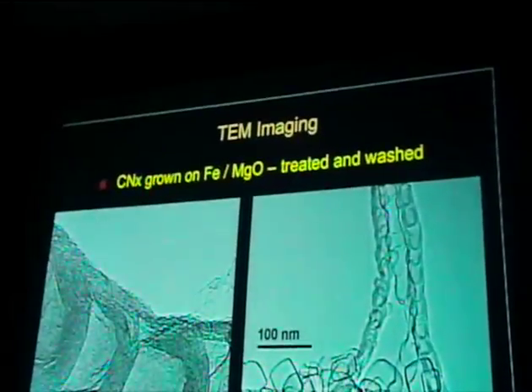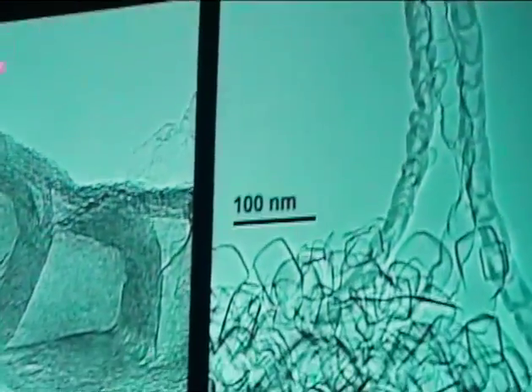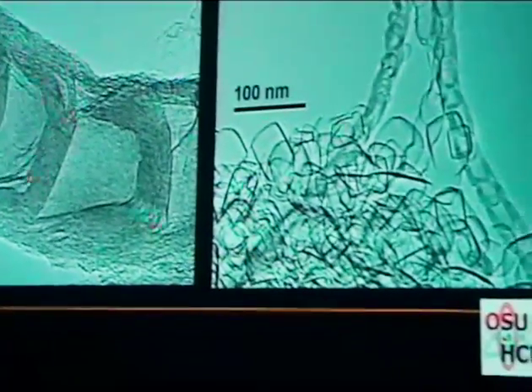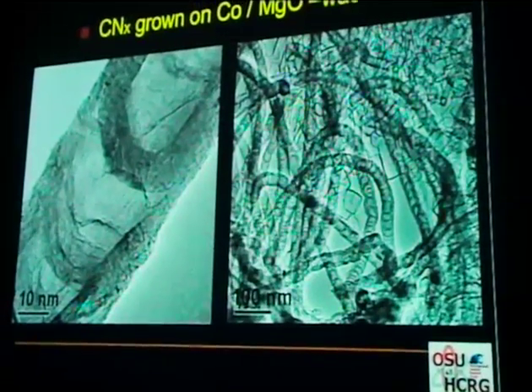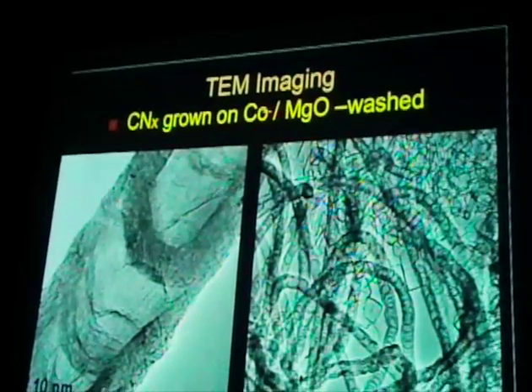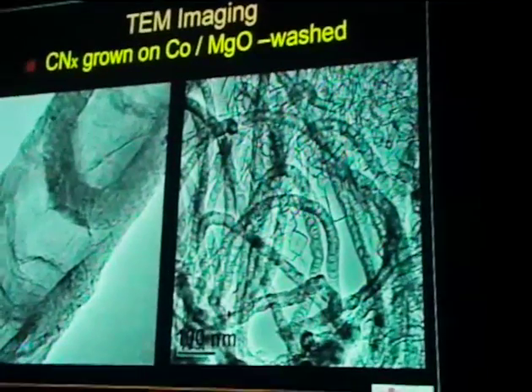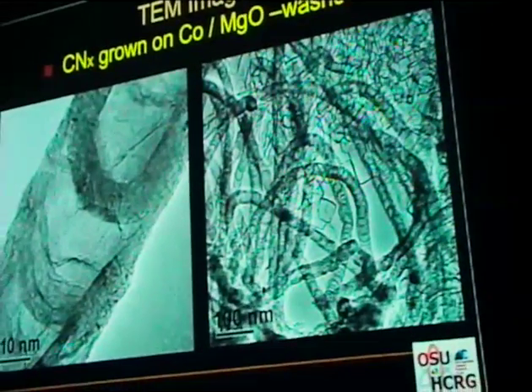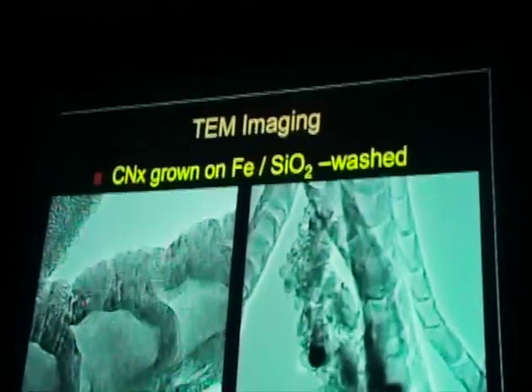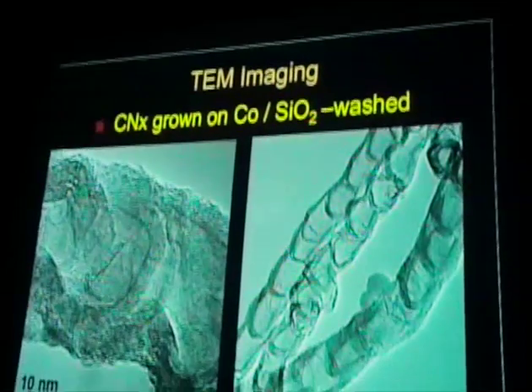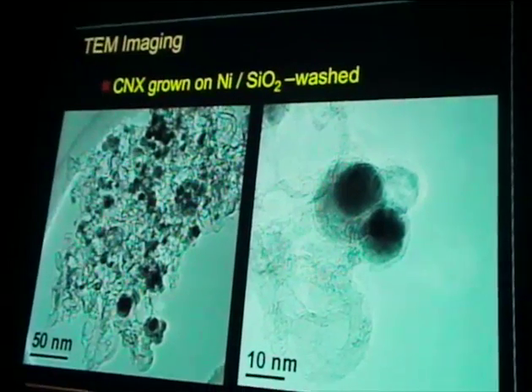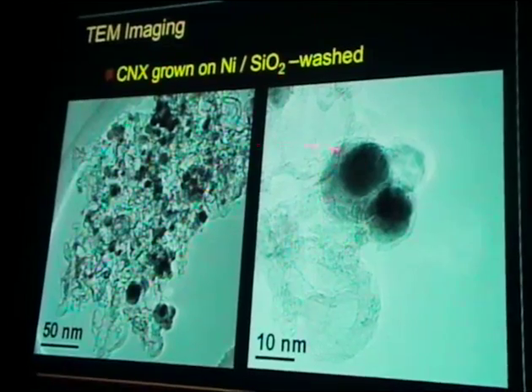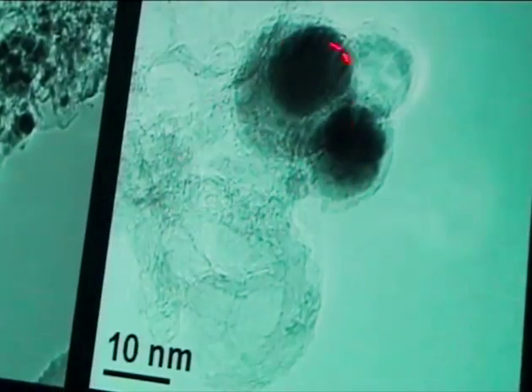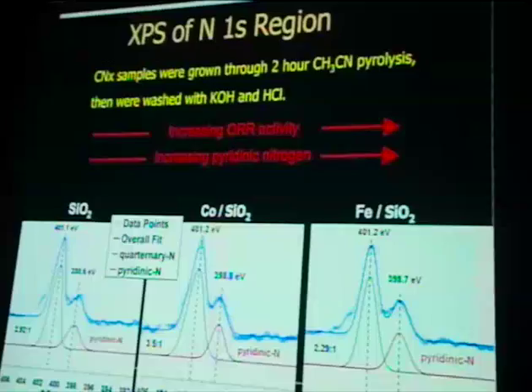Here is iron-containing magnesia, the CNX samples grown, and again, you can see the stacked-up structures. And a closer look, this is cobalt. We have tested cobalt. It's also giving a very good performance, cobalt on magnesia, so CNX fibers grown on this support. Iron on silica, cobalt on silica, and for example, nickel on silica: we don't see any fibers, but we see mostly these onions. And this also has very, very poor oxygen reduction reaction activity.